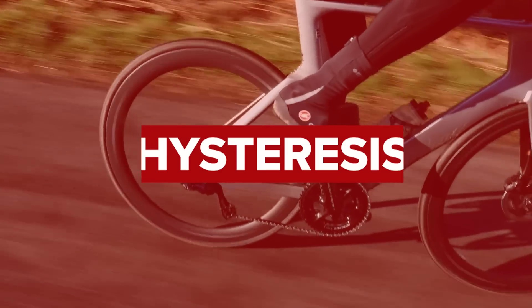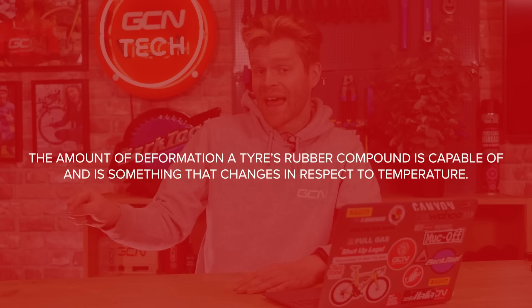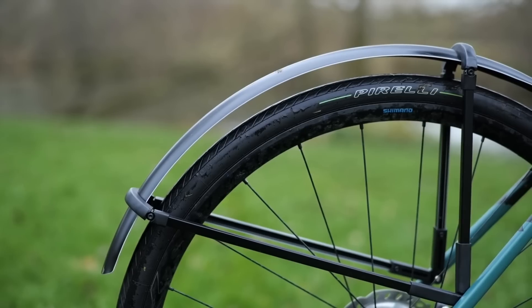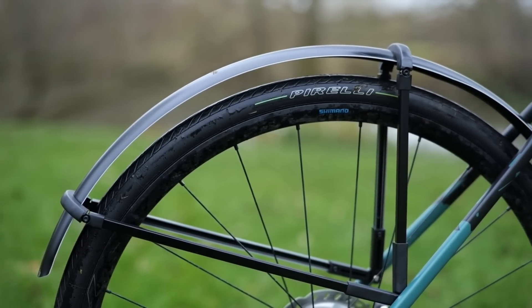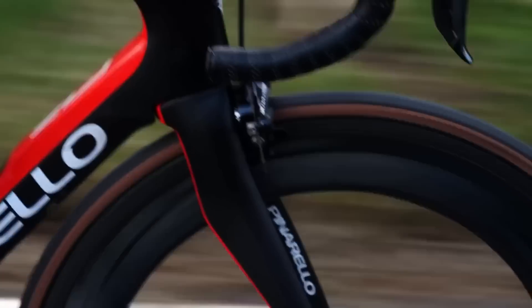This is why hysteresis is so important. Hysteresis is one of the main characteristics behind a tire compound's performance. It's the amount of deformation a tire's rubber compound is capable of, and it's something that changes with respect to temperature — that is the main reason why we have summer tires and winter tires. When you freeze natural rubber, it becomes brittle and hard, and therefore it can't deform over those imperfections in the road, meaning less contact area and less grip. Tire companies can manipulate and tweak the tire compound so that it's more supple in low temperatures — that's why special compounds are found on winter tires like the P Zero 4S compared to a summer tire like the P Zero Race, which would be a lot stiffer in cold conditions. It's also why motorsport drivers heat up their tires — cold tires don't deform and therefore don't grip as well.